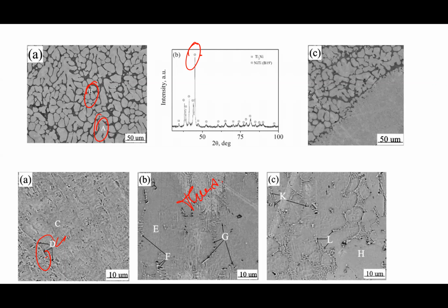The interdendrite space includes two phases, a white area marked as F and a dark area marked by G. The EDX result shows that the volumes have different compositions, and the phase marked by F is a titanium rich NiTi phase with a titanium concentration of 52.3%, whereas the area marked by G is a Ni rich NiTi phase containing 51.3% nickel. So the main volume of the third layer was occupied by the dendrite matrix, which is a Ni rich NiTi phase having 49.5% of titanium and 50.5% of nickel.